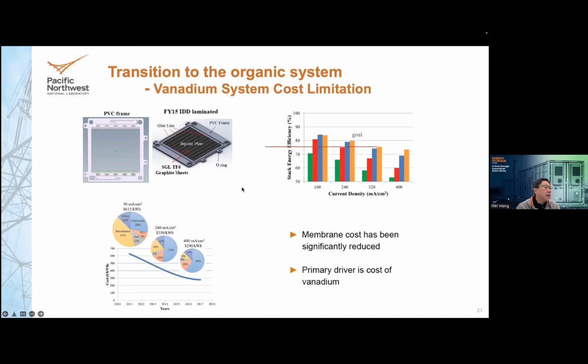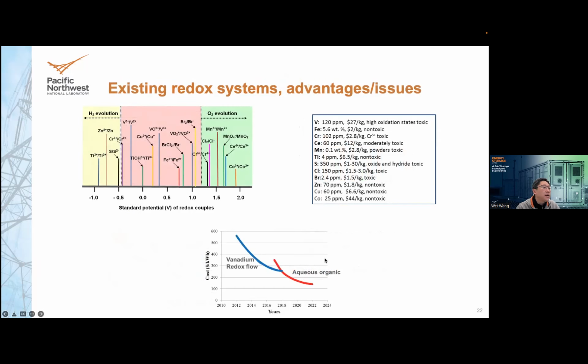What that does is significantly change the cost distribution of the overall vanadium system. Early on, the membrane was one of the major costs, at 42%. But once you increase the current density, the chemical itself becomes the major cost driver at 60%. So we have to find some other cheap materials to replace vanadium as the energy bearing material. As I said before, if you look at the redox potentials of inorganic transition metal ions or other elements and consider their availability in the Earth's crust, there's not a whole lot of choice. That's the reason why the whole field is jumping into the organic system.